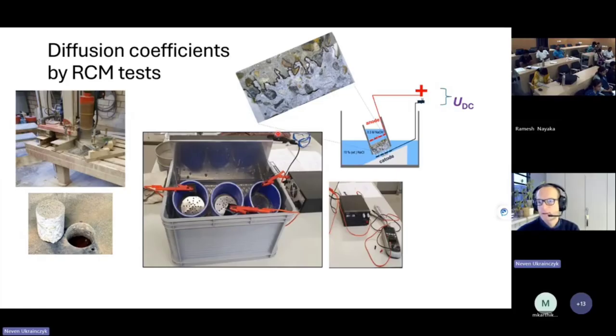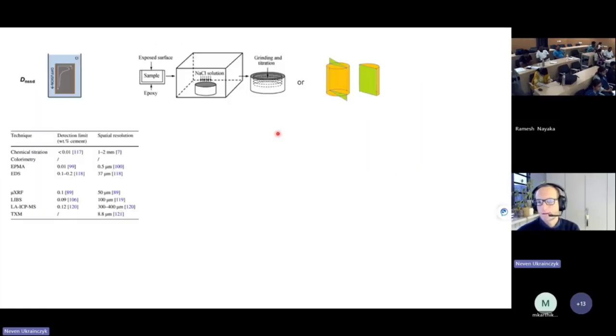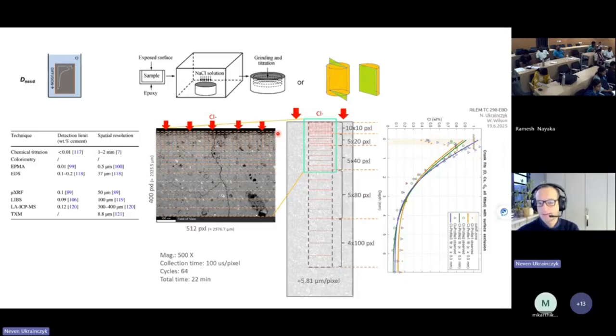So that's how the RCM, rapid chloride migration, looks like in our lab. And we are now making a round robin test in this technical committee, that we have 4 different mixtures: the ordinary Portland cement, fly ash, with blended the slag, and with the LC3, with the limestone and the clay, 30% clay, 33% clay, the LC3 mixture. And on those mortars and pastes, we had 1 year exposure, sorry, 1 year hydration. You have these samples, and then the exposure for 28 days to sodium chloride solution, 0.5 molar. It's coated in epoxy, so that we have one-dimensional diffusion.